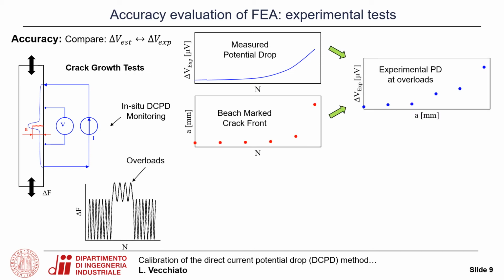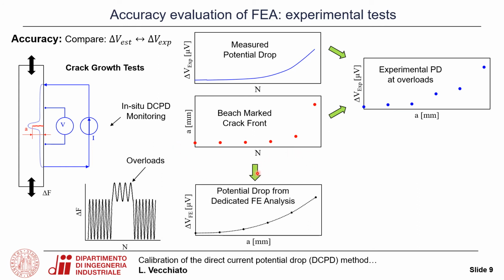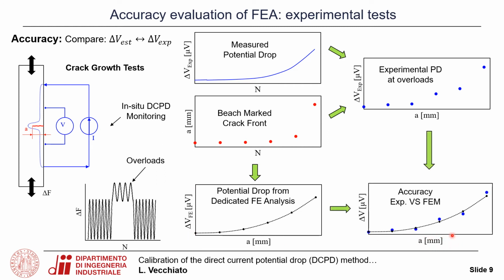For having the experimental value of the potential drop compared with the real crack size and shape, some overloads have been introduced over the constant amplitude fatigue test for benchmarking the crack front and obtaining an experimental calibration curve for the potential drop method. From the benchmarked crack front, it was possible to realize dedicated finite element analysis so as to obtain the estimated value for the potential drop to be compared at last with the experimental one, so as to evaluate the accuracy of the measure.